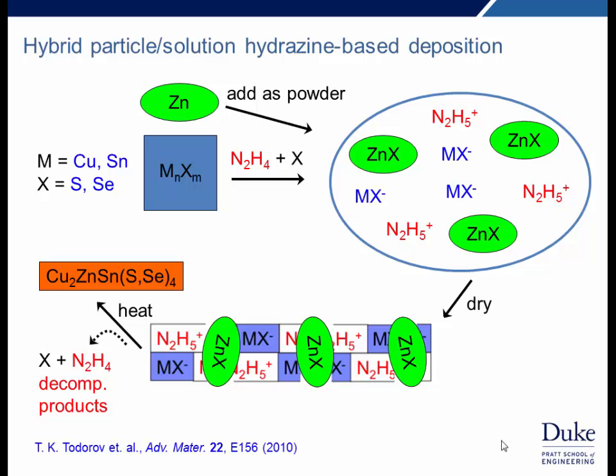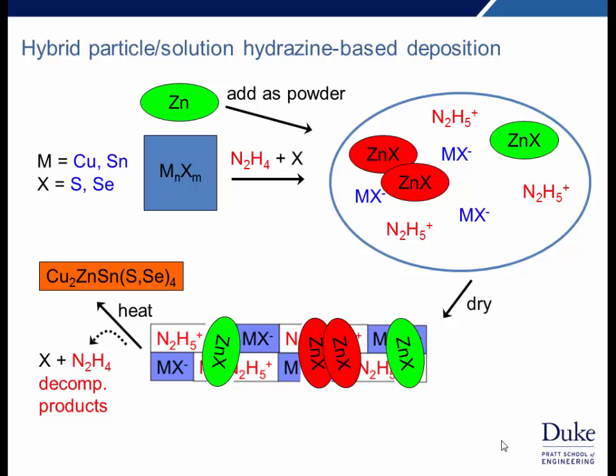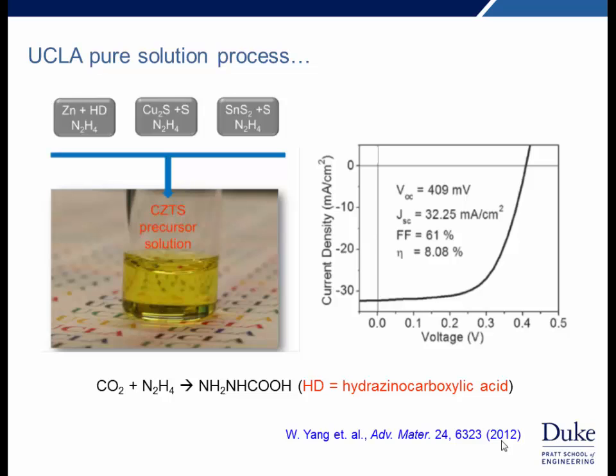And one of the first areas we looked at was maybe our deposition process is contributing to this. Namely, if we consider a slurry approach, most people who've worked with particles will understand that particles like to aggregate. And if they aggregate, this can lead to non-uniformity in the precursor film and ultimately in the final film. And so we wanted to look for ways of creating a pure solution approach for the zinc-based system. And one approach was reported by the UCLA group, where they reacted carbon dioxide with hydrazine to create this hydrazinocarboxylic acid derivative, which coordinates the zinc and enables the creation of a pure solution.